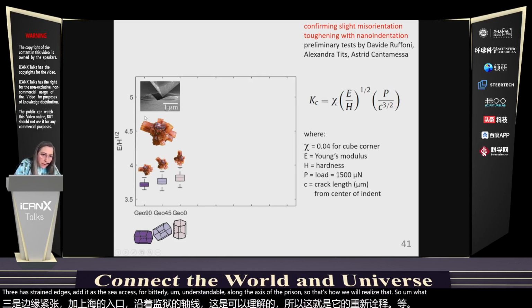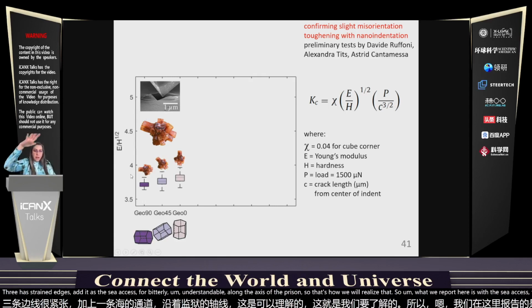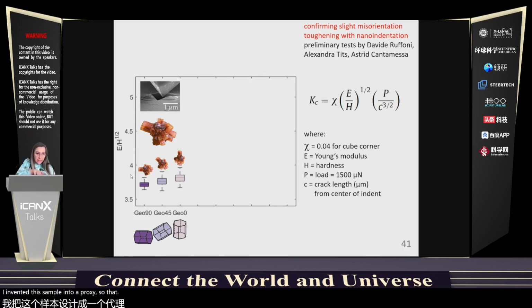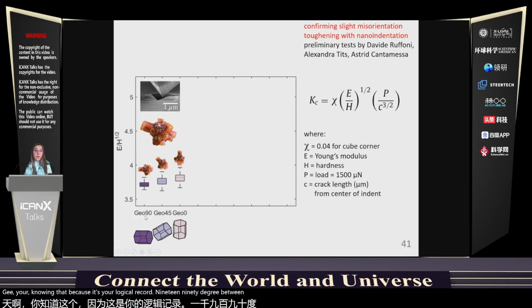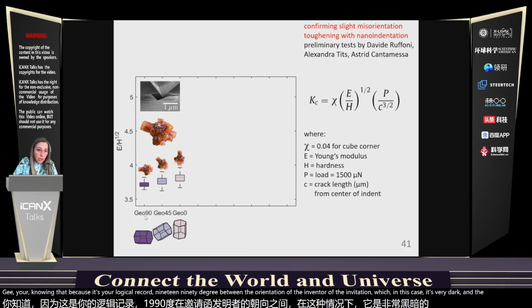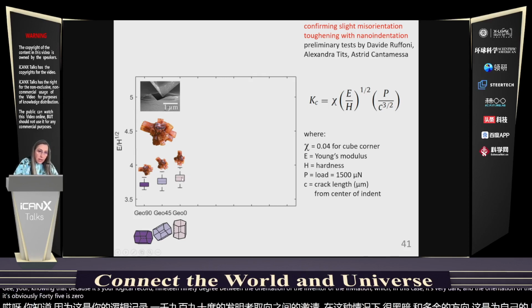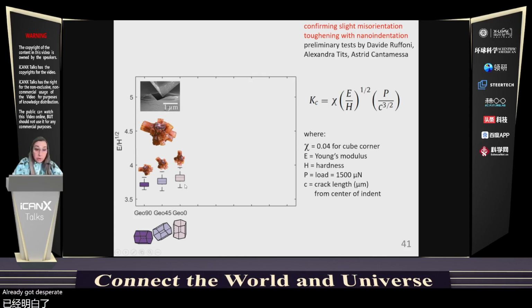So what we report here is with the C-axis horizontal, meaning I embedded this sample into epoxy so that the C-axis is in plane and then polished through. Obviously, for nanoindentation, we need a flat surface with the C-axis in plane, parallel to the plane of the polishing plane, and perpendicular to the indent. And so that's why we call this Geo 90, because it's geological Aragonite, and 90 degrees between the orientation of the indenter or the indentation, which in this case is vertical, and the orientation of the C-axis, which is horizontal. So that's Geo 90. 45 degrees is obviously 45, and 0 degrees is with the C-axis vertical. That's parallel to the direction of indentation. These are the prisms oriented as I just described.